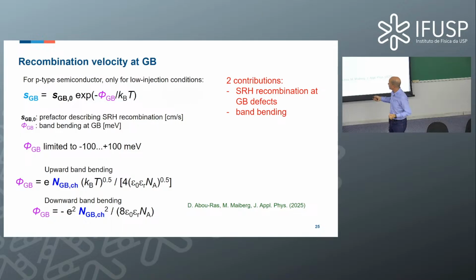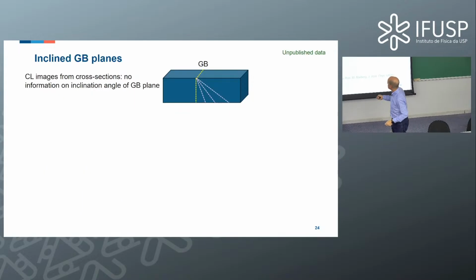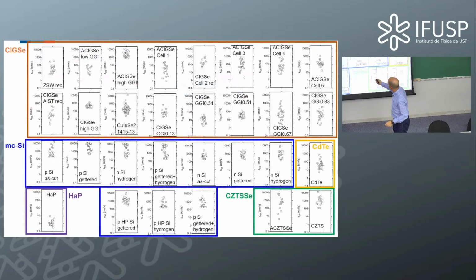But we have an effect on the recombination because this magnitude here is changed quite drastically by the exponential function, right? So we can imagine a very small change in this barrier height already invokes a very large change in the recombination velocity. And this makes the large range of recombination velocity values that we can find for each and every material system here. Yeah? The fact that we find such a behavior is because of the exponential function.